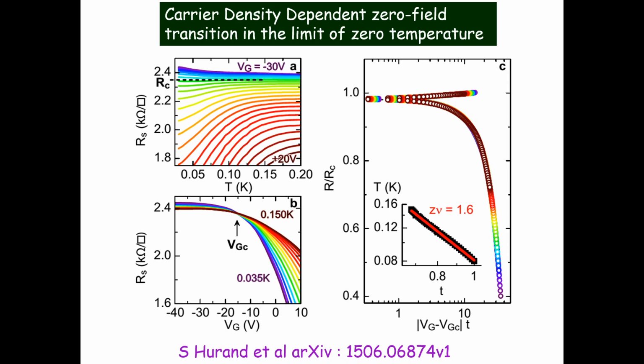Now, what we are going to do is do the same thing. The tuning parameter is the carrier concentration. So, the carrier density dependent zero field transition in the limit of zero temperature. These data are for LAO-STO, and you are starting at plus 20 volts. So, there is a transition here, this is superconducting, and as you go towards negative voltage, somewhere here you see that your sheet resistance is actually independent of temperature, and above this voltage you start entering the regime of a dirty metal. So, again we define a critical value of gate voltage, or in other words a critical carrier concentration, at which we enter the superconducting phase.